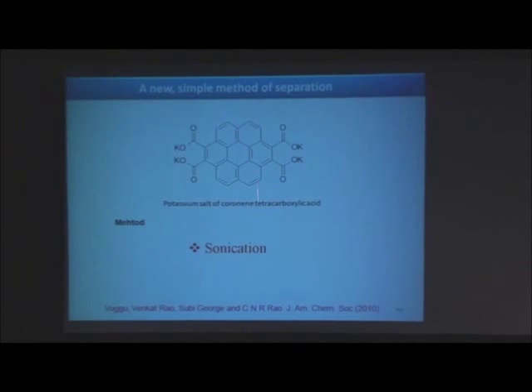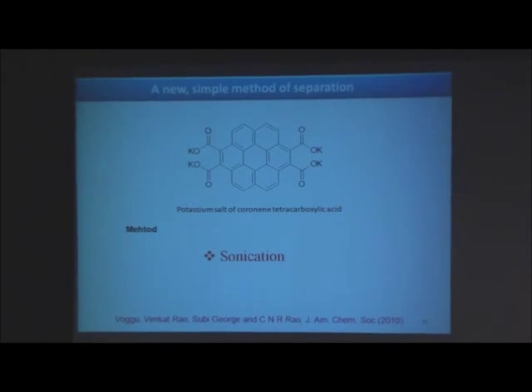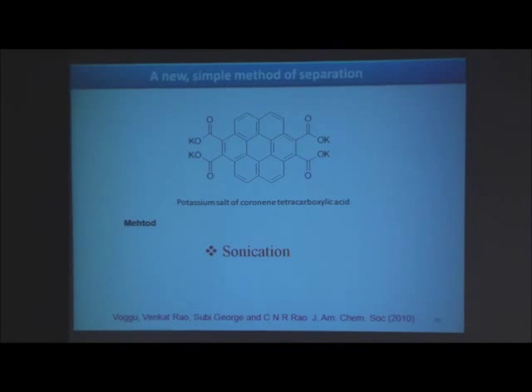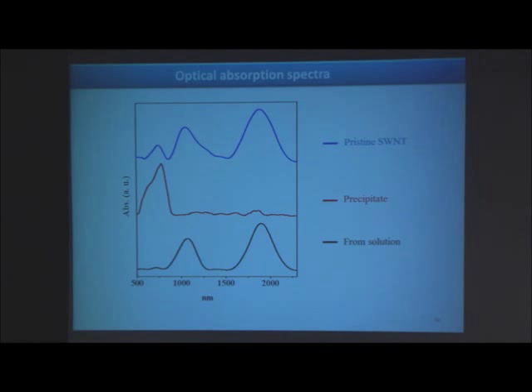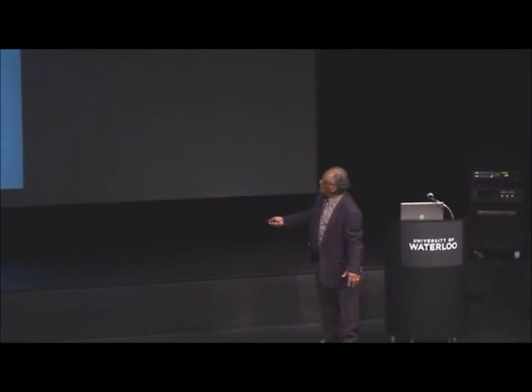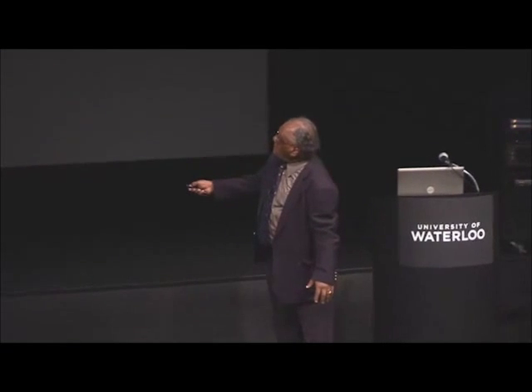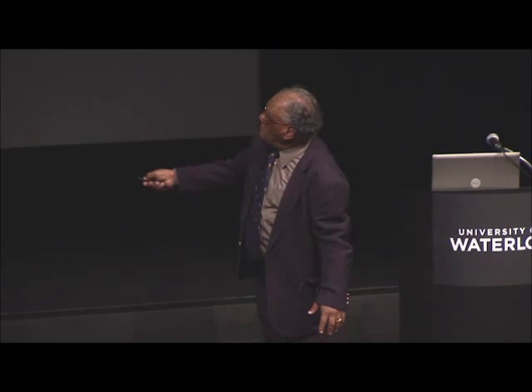So I use this charge transfer idea to separate metallic and semiconducting nanotubes. What we did is take the same molecule which had separated the layers of graphene, tetracarboxylate of coronene, a very good pi system. I put that in a mixture of nanotubes which are both semiconducting and metallic species. And what it does is it preferentially gets stuck to the metallic nanotube because of the electron density. And the metallic nanotubes precipitate out under the right conditions. And then you take the spectrum. The precipitate starts with metallic nanotubes, that little peak, and these two semiconducting peaks. This is the optical spectra. The precipitate has only metallic nanotubes. The solution has only semiconducting nanotubes in one step.